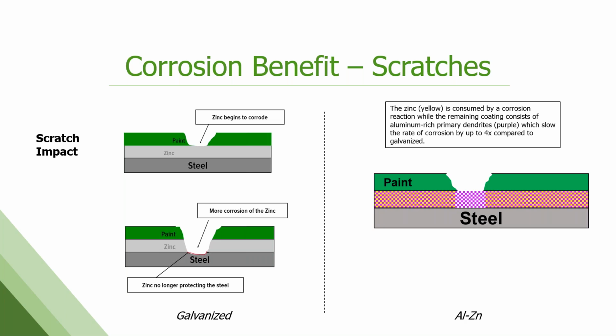So on the left, we have galvanized, right? So it's painted, you have your layer of zinc and then your steel. You get a cut or a scratch to that painted surface. Now you're down to exposed zinc layer. That zinc is going to sacrifice itself to protect the steel, but eventually that's going to run out and you're going to get down to base steel, at which point you're going to start to get unsightly red rust bleed through, which no one wants to see. However, on the right, we have the aluminum zinc product, right, which is that matrix of aluminum and zinc together. So yeah, the zinc, the yellow in this picture, goes away, but you're left with all this purple. The aluminum's still there, which is still protecting the steel. So you're not down to steel yet. And it still is allowing that paint all around the edges there to adhere to something. It can't flap free, right? You don't get that paint peeling effect that you might get on galvanized.